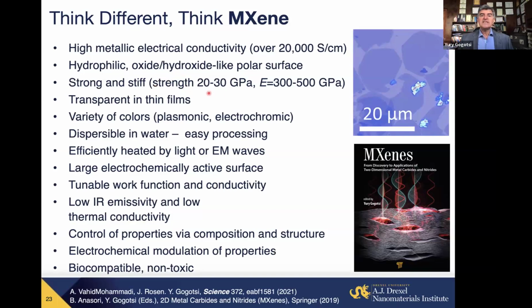But they're also extremely strong. I've shown you films assembled from these flakes. And they're strong because the flakes are very strong, extremely strong. Those are single flakes of Ti3C2 MXene on a silicon wafer. That's an optical photograph in an optical microscope, not an electron microscope. Those are single layer flakes, but you see they're about 20 micron size.